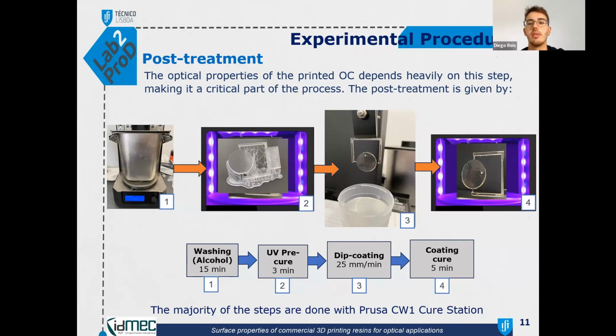So first is the washing in alcohol of the printing, then UV pre-cure to cure the remaining resin, and then the support structure is removed and the frame is attached to the dip coating equipment, and the coating is done with a withdrawal velocity of 25 millimeters per minute. Then the coating cure.